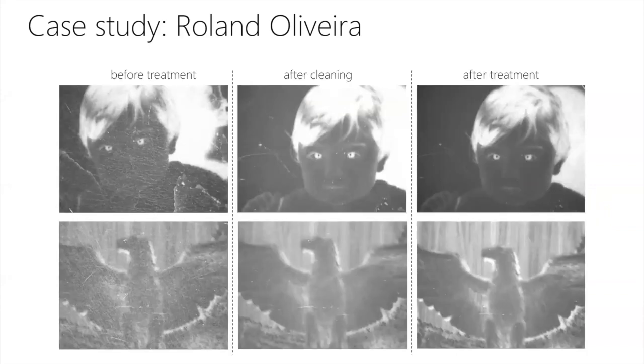The effectiveness of the treatment was monitored using a digital microscope. Here you can see the image before treatment and after the cleaning procedure, where you can see that the fungi was successfully removed and no abrasion was added with dissection. Based on the collected images and on the observation with the naked eye, the developed unwinding and flattening treatment did not damage the image of the negatives.